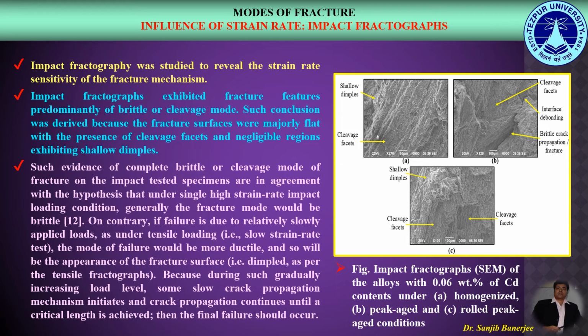To study the influence of strain rate, we investigated the impact fractographs over here, which exhibited fractured features predominantly of brittle or cleavage mode, because the fracture surfaces were majorly flat with the presence of cleavage facets and negligible regions exhibiting dimples.